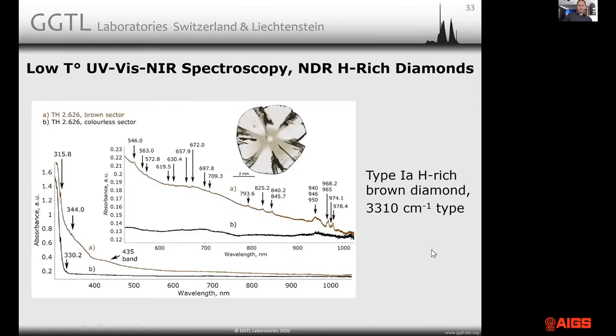In comparison to this, the cuboid octahedral stone, the striated diamond, here spectrum A is of the brown sectors, spectrum B is of the colorless sector. Colorless sector, you can see there is just nothing. It's just no absorption whatsoever. And then at 330, you get up to the cutoff at about 310 nanometers.